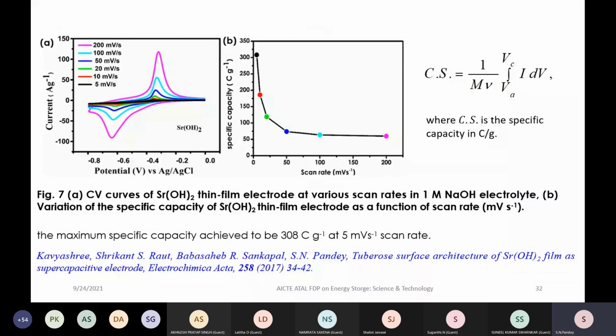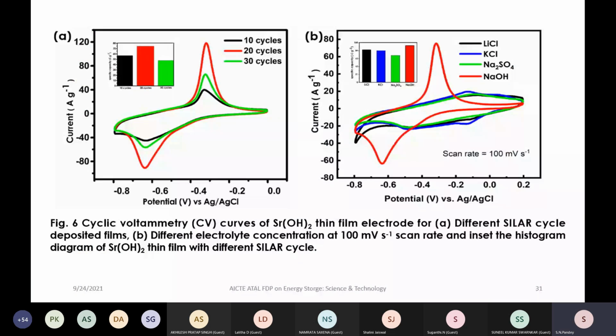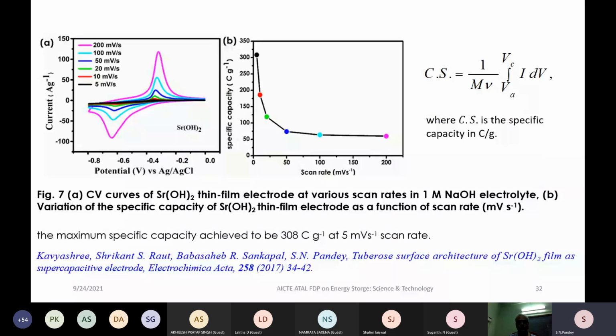Then this is the CV curve at different scan rates in 1 molar NaOH electrolyte. I have not discussed the electrolytes, but one can see that for NaOH, the CV curve has the largest area. So we optimized it here, and then for the different scan rates, from 5 millivolt per second to 200 millivolt per second, that we have put there.